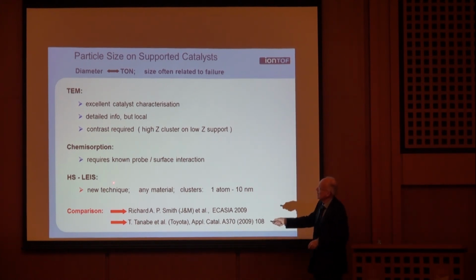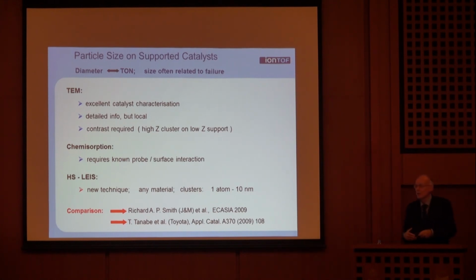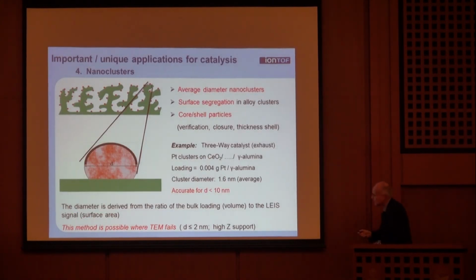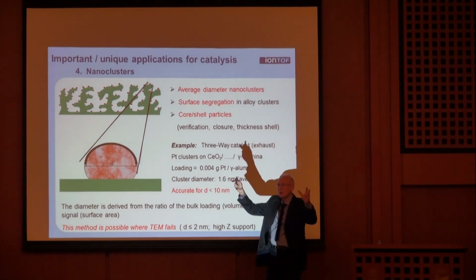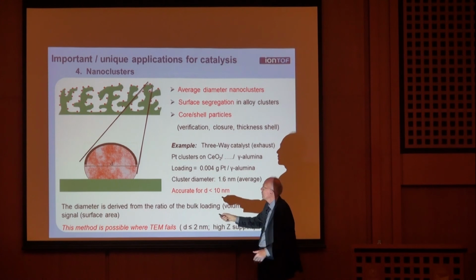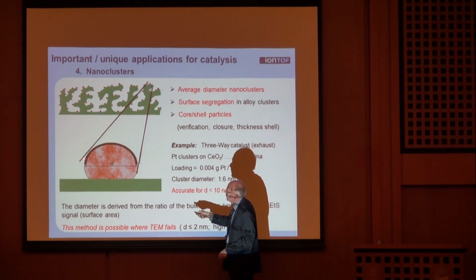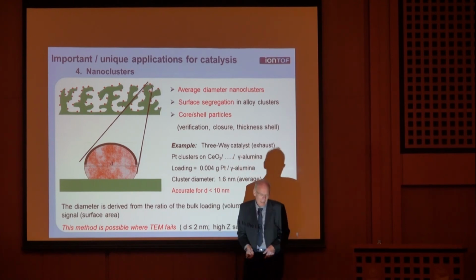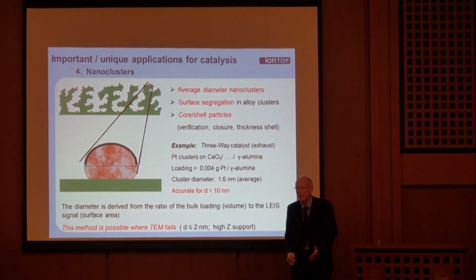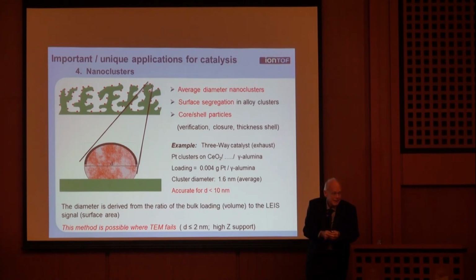We combine these techniques with low energy ion scattering, and I'll show you how we can determine the size of these clusters. If this is a real catalyst, a kind of cartoon, small clusters on top, something very rough. If I look at one of these nano clusters, in ion scattering I will see the top layer. If I use a bulk chemical technique, I learn how much platinum there is in total. I know the volume, here I know the surface, and the ratio of volume to surface gives me the diameter.